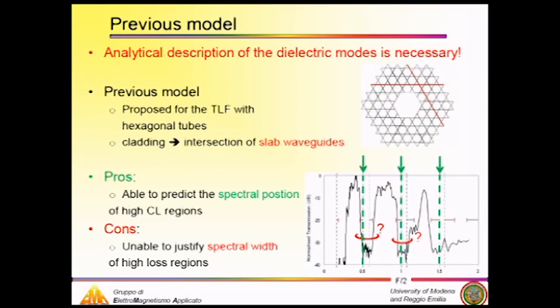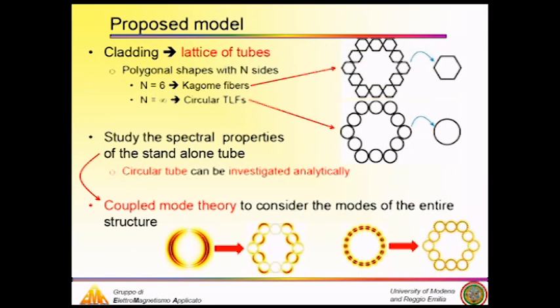The previous model that has been proposed in the literature was just for the Kagome fibers, and it models the cladding as an intersection of slab waveguides. It's very simple as a model, and it is able to predict the spectral position of this high loss region. But at the same time, the main lack is that it cannot predict the spectral width of this high loss region. So our idea is that in both Kagome and tube lattice fibers, the cladding can be composed as an arrangement of tubes. Of course, what changes between the two structures is the shape of the tube.